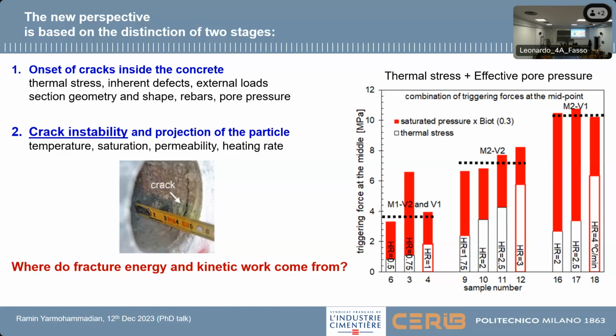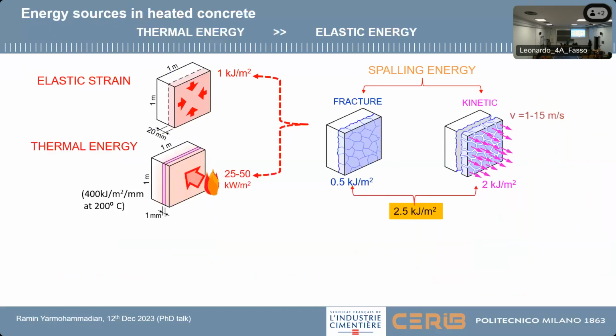For the second stage, the main question might be, where do the fracture energy and kinetic work come from? We should find the real source of energy which we deal with in this spalling event. As I mentioned, the whole spalling event consists of two stages. If we sum up the energy that we need for the whole spalling, we need energy for the fracturing of the concrete, which is about half a kilojoule per square meter for 1 meter by 1 meter of concrete. Then for accelerating those particles, we need about 2 kilojoules per square meter. If we sum up both, it's 2.5 kilojoules per square meter that we need for the spalling.